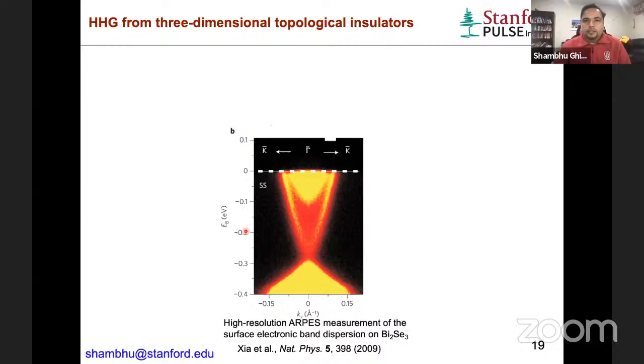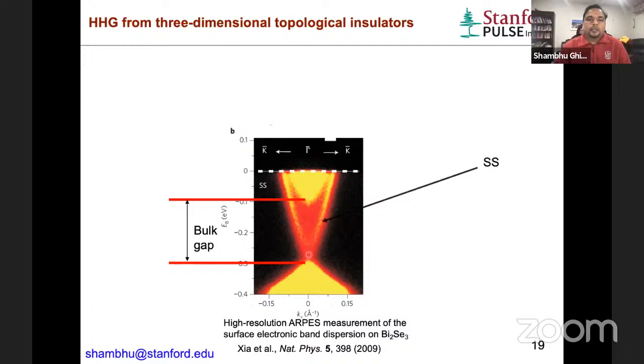So this is the ARPES measurement where they were able to nicely see the band structure of bismuth selenide. You can see here these are the bulk bands with high intensities, the valence band and conduction band. And there is a certain band gap, right? Also, this is a nice Dirac cone that does not have any band gap, connecting the valence and conduction bands. These are the surface states. So this is the nice signature of topological insulators. You have the bulk insulating, and the surface does not have a band gap, and also these states are time reversal symmetry protected.